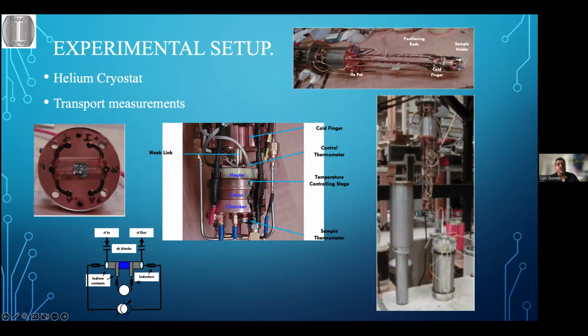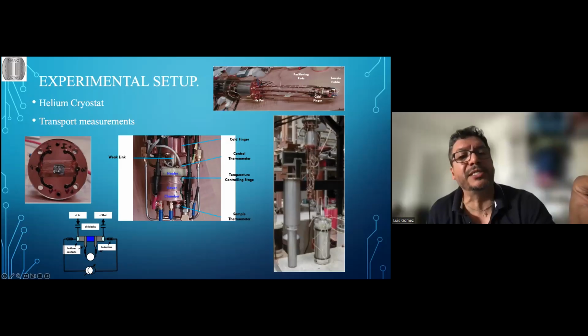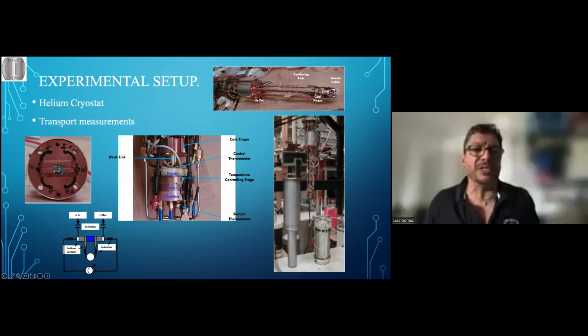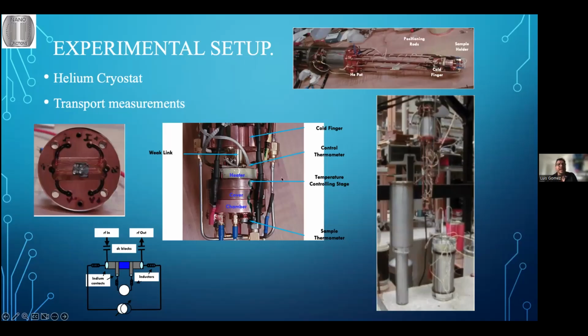And then closer to the sample, we have another cold point that can be variable. There is a resistor here that can change the temperature of only this part. Actually, this is the cold finger, so this is the 4 kelvins. But then this will be a heater. There is a weak link here. It's made of brass. This is copper. So whenever we change the temperature of this region, that will change the temperature where the sample is. And then we have a couple of thermometers so we can control this really well. So this type of system gave us very stable control of the temperature, in the order of millikelvins.